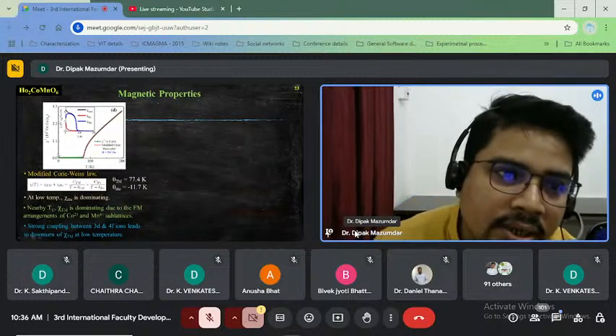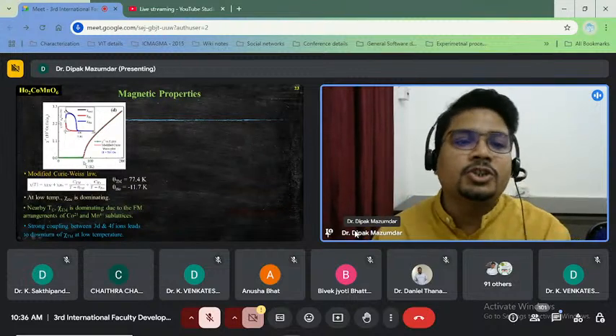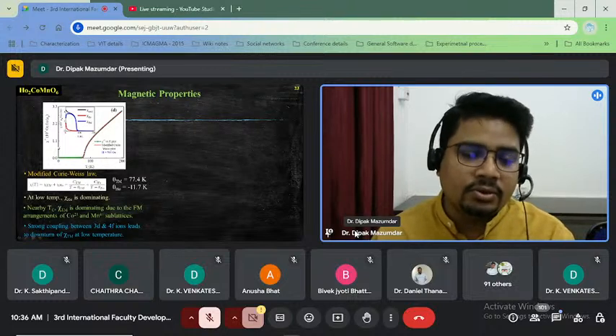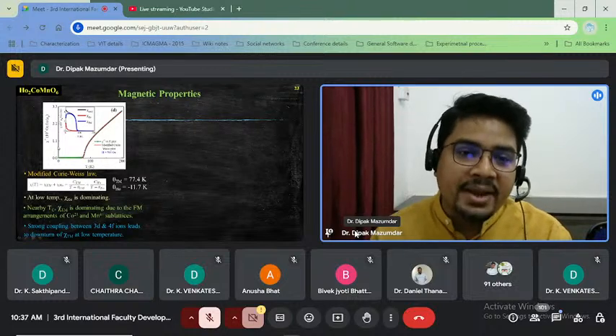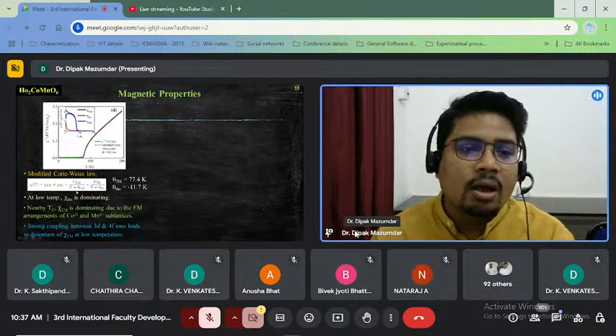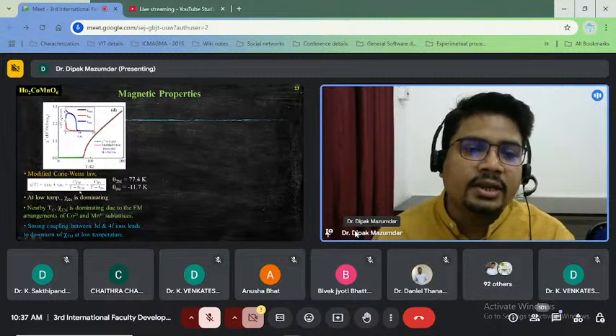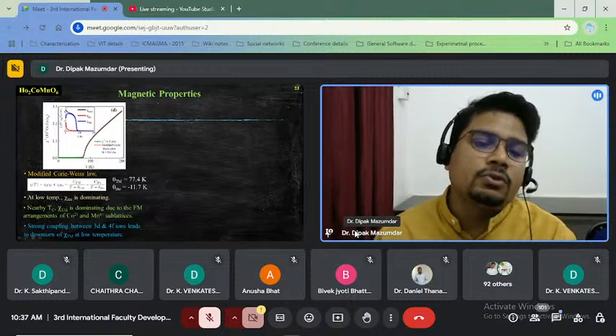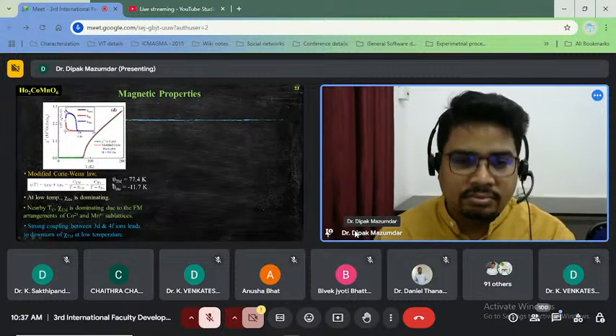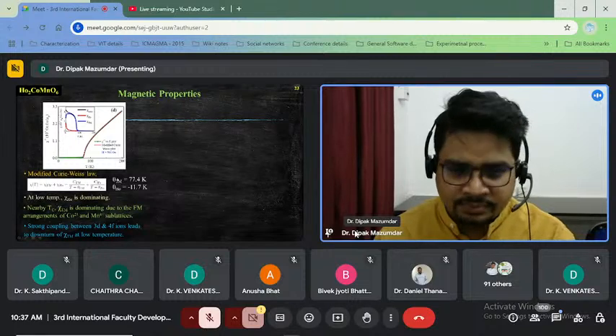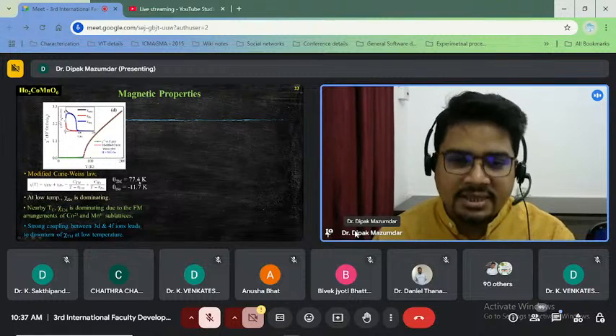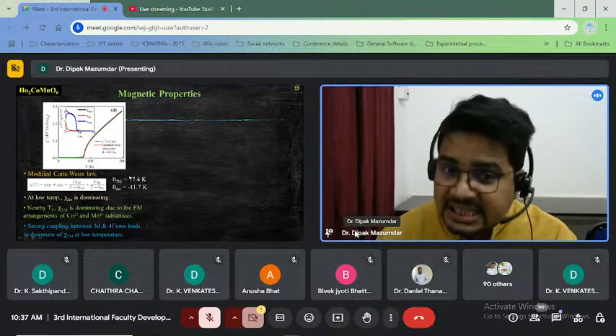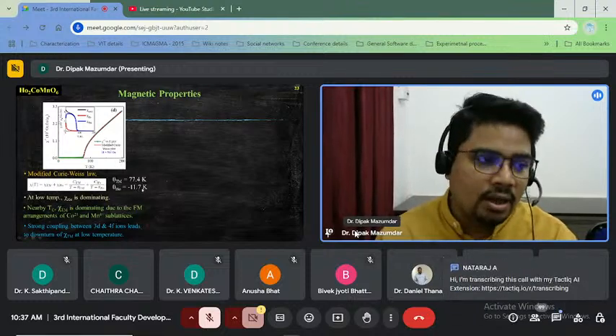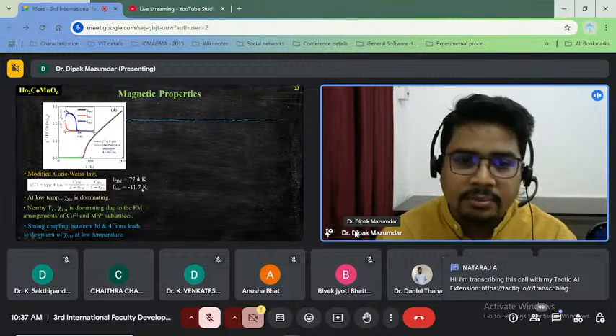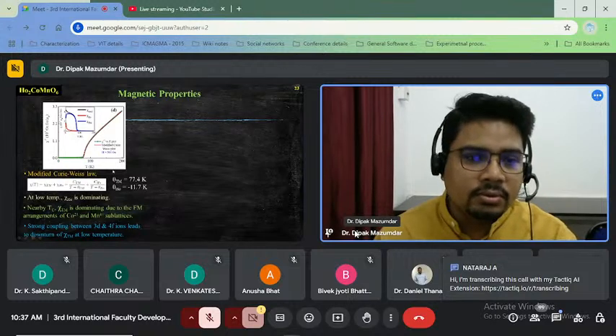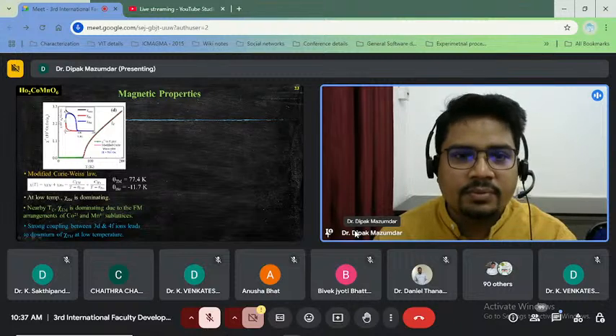Next, I am discussing the inverse susceptibility as a function of temperature plot, because this is very important to understand the contribution of magnetic ions. I have used this modified Curie-Weiss formula to fit the data. From this fitting, I get theta for the transition metal ions around 77.4 Kelvin, which is near our TC, and for holmium around 41.7 Kelvin. So this shows a very good fitting.